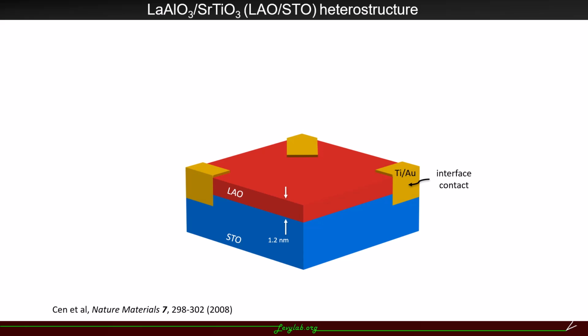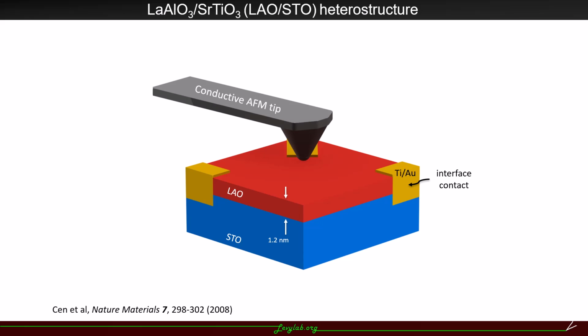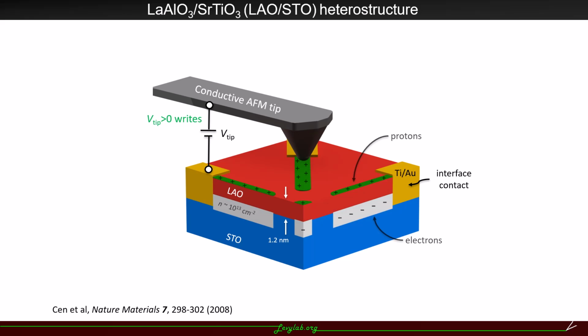Our experiment uses conductive atomic force microscope lithography, c-AFM lithography, to pattern the interface on the nanoscale. We start with lanthanum aluminate strontium titanate, about 3-4 unit cells, so it is insulating to begin with. We make electrical contacts to the interface. If we take a conductive AFM tip, apply a positive voltage to the tip, and move it across the surface of the material, it will deposit protons and attract electrons, creating conductive channels. The process is reversible. If we apply a negative voltage, we could erase the structures and create barriers. These nanostructures can be as small as 2 nanometers. Nanowires created in this method undergo superconducting phase transition at 300 millikelvin.